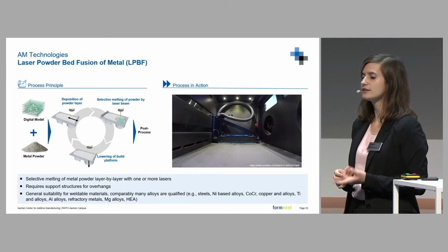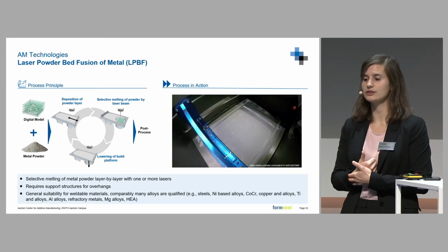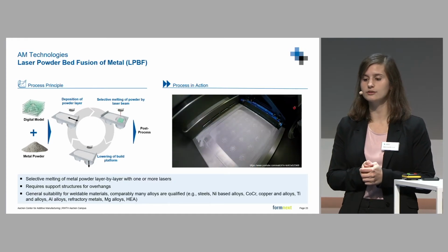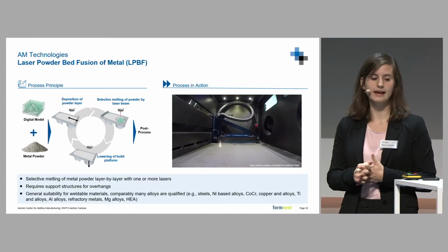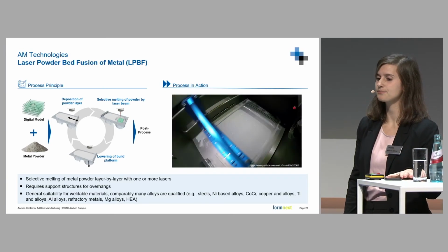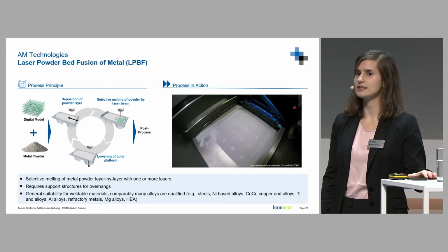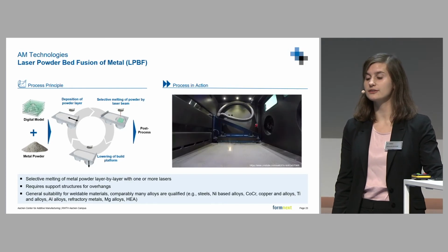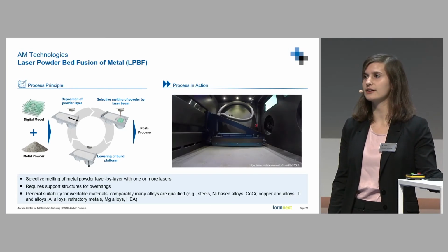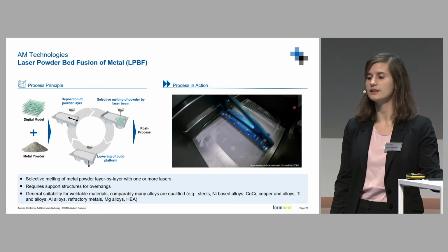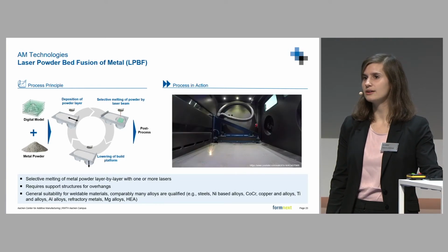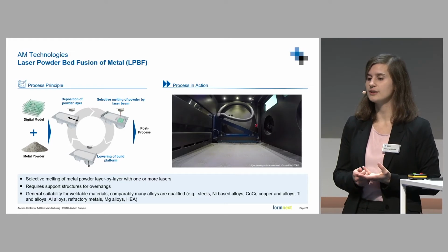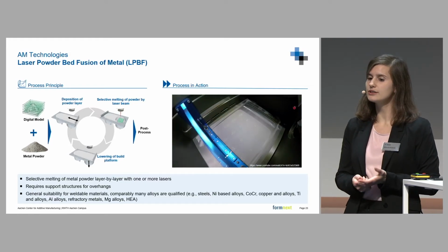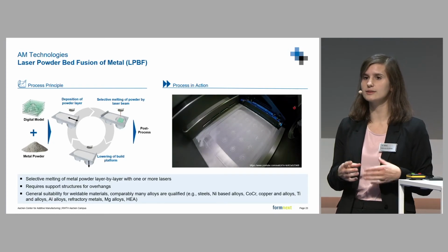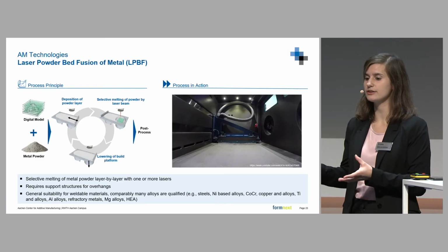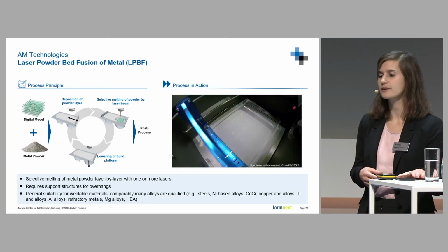For example, you can use steels, nickel-based alloys, copper, titanium, aluminum, magnesium, it doesn't really matter. You're not really limited in choice of material. Laser powder bed fusion is the technology that's mostly used in industrial applications, so it has a very high process maturity. For example, AM Power always publishes a report on the technology maturity of different AM technologies, and laser powder bed fusion is the technology with the highest technology maturity reached, so it's a very stable process.